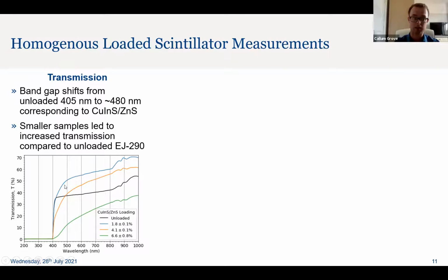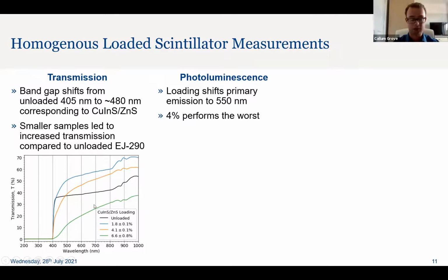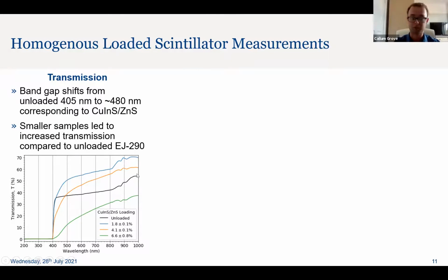Whereas in the loaded sample, the transmission plateau doesn't start until about 600, which is consistent with an additional band edge corresponding to the quantum dots' absorption. That was about 480 in these transmission spectra. It should also be said, we were expecting the transmission of the unloaded scintillator to be higher. However, when polishing, we ended up polishing more material off these two samples, and so we ended up with an artificially high transmission because we have a smaller sample.